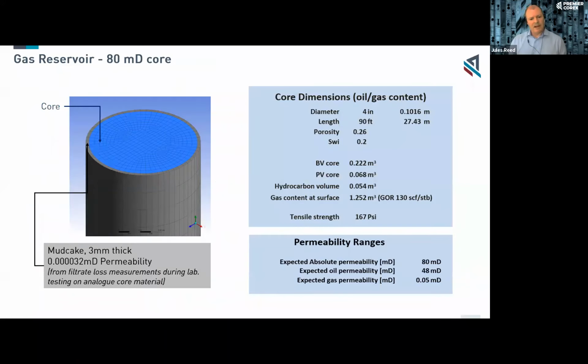And what we do there is we build a mesh of the core, a simulation of the core. We apply the core properties. We also apply liquid properties. We may also simulate the mud cake. That becomes important, as you'll see in the next couple of slides. And once we've put all the properties on there, one of the big properties to consider is the tensile strength of the core. And the tensile strength is basically equivalent to the unconfined compressive strength. It's about 1/10 of the unconfined compressive strength.